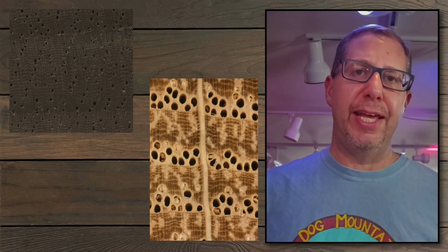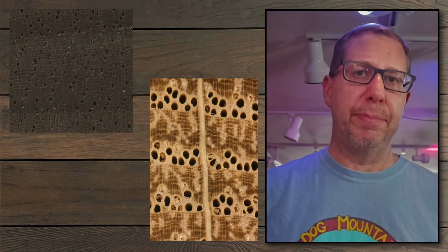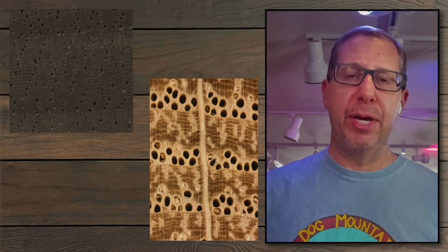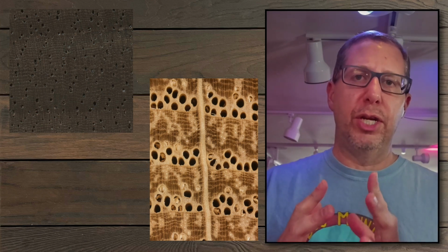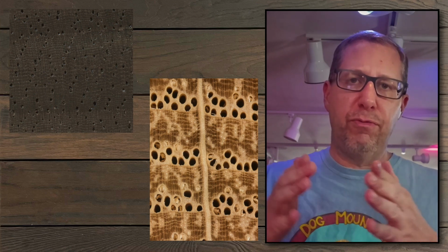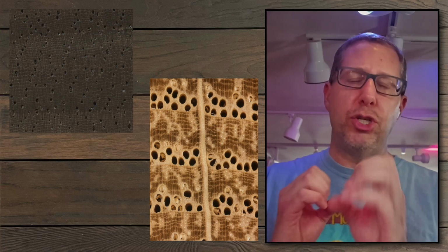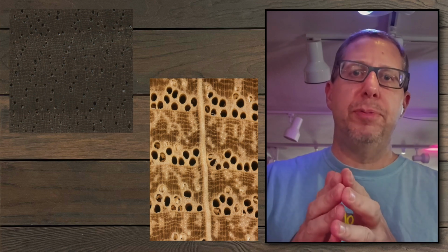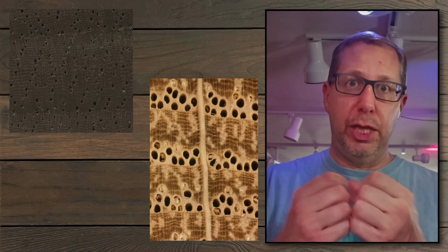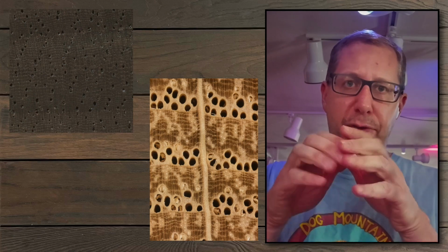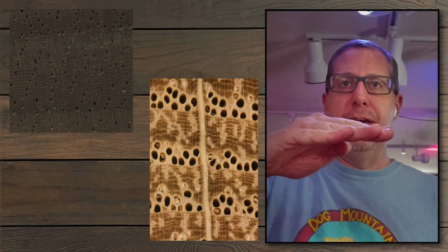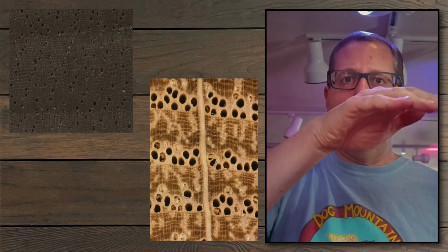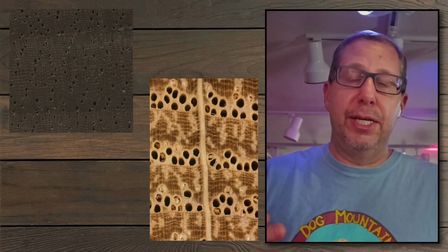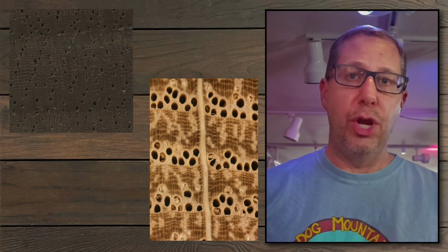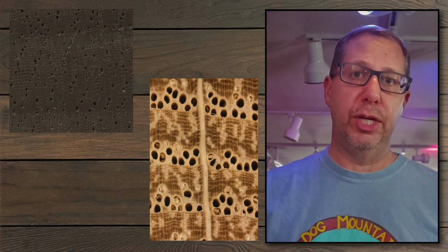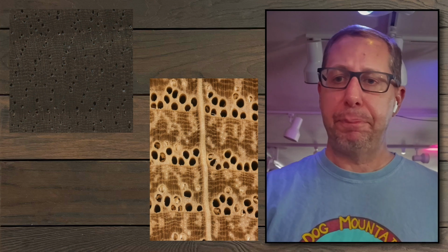And what you find is walnut is really prone to cell collapse as you're drying it. As things are heated up, there's so much pressure, there's no place for that water to go. The permeability is so low that all the water is forced into those pits. And with that pressure of the water moving through those specific areas, it can actually cause that cell wall to collapse. And sometimes it even implodes on itself. You look along the surface of the board, and you'll see these kind of undulating parts where the cell wall has just given up and literally collapsed like a house, because there's just no place for the moisture to go through.